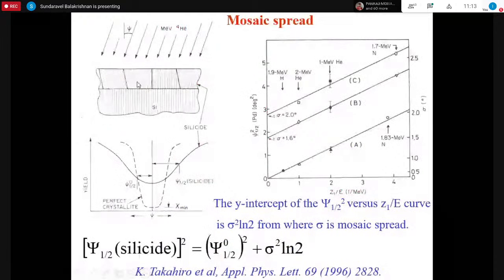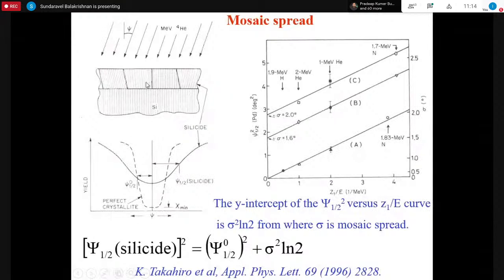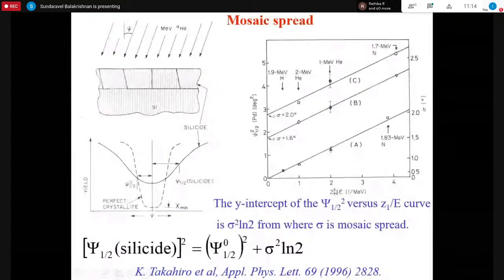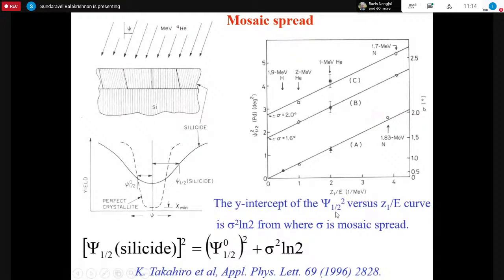So in that case, for an ideal crystal, it would have been like this dotted curve, but due to this mosaic spread, where you have some plus minus small angle of misorientation of these domains, it will be somewhat broadened. And if you take this tilt angular curve for different energies, and plot the width of the curve squared divided by Z1 by E, the energy, then one can find the slope, and that slope will give information about this mosaic spread sigma.